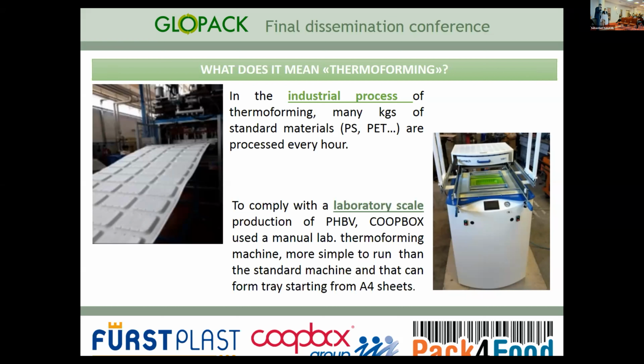Since the quantity of material involved in the Glopack project was lower than that, we decided to move to a laboratory scale machine that was able to thermoform the sheet provided by Fraunhofer. Here you can see the comparison. On the left there is a standard thermoform machine with a high production, with a lot of cavities in the mold. It's around 20 or 24, so you can produce 24 trays every cycle.